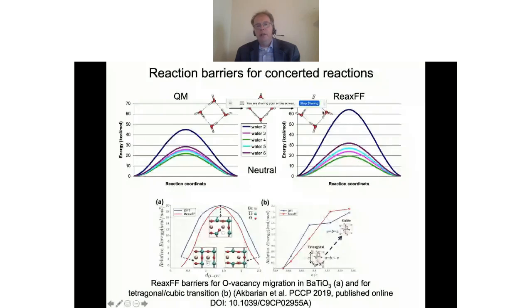And it can do that because it has this long-range bond order. So even when we are at the transition state, we still have nice, the total bond order is conserved because we have these half bond orders. So instead of having bond order of 1 and 0, we get a whole bunch of bond orders of close to 0.5. And so that means indeed the total energy that we need is relatively low.